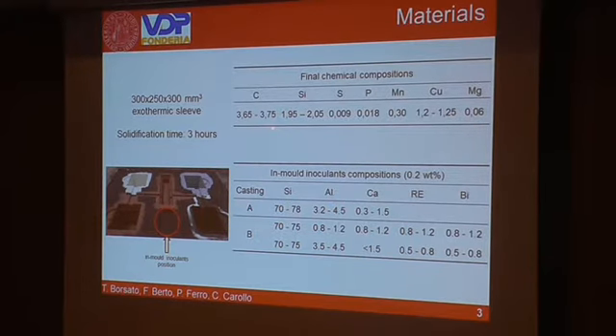The material that was used was a perlitic ductile iron, whose final composition is reported in this table. 2 castings, named A and B, were produced with this chemical composition and with different inoculation treatments. The first casting, named A, was inoculated with inoculants containing silicon, aluminium, and calcium, while the second casting was inoculated with inoculants that contain also rare earths and bismuth.